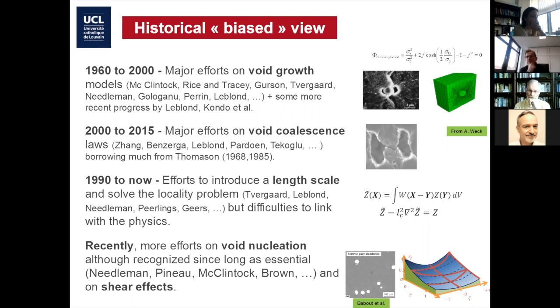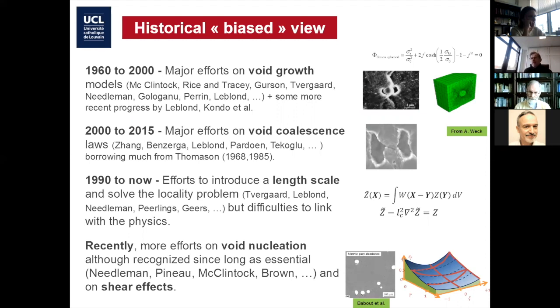Something like 20 years ago, people realized there was a real recruited sense of interest for looking at the final step: when the voids are big enough, they try to interact, and the process of growth is accelerated. This is called the void coalescence process — when plastic deformation stops being homogeneously distributed around the voids but then localizes in the ligament between the voids, in terms of internal necking or a small shear band in between. People realized this is really the phenomenon of fracture — the initiation of the fracture process — and so it's very important to have dedicated models to predict that.